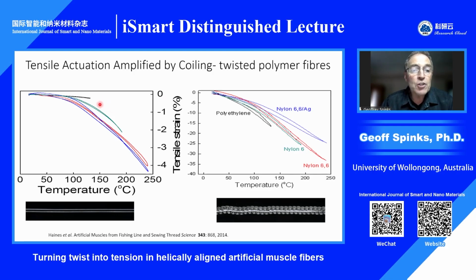And you can see that they contract in length a little bit as they're heated, and that's reversed on cooling. So this contraction in length, even though the volume is expanding, there's volume thermal expansion occurring, the length actually decreases a little bit because of the highly oriented crystal structure in these materials. Now you take the same fibre and twist it and coil it and then heat it, you can see you get the same shape curves, but the scale is now 10 times larger. So we can easily see contractions of 20, 30, or even up to 40%.